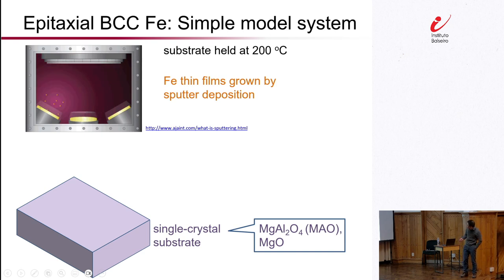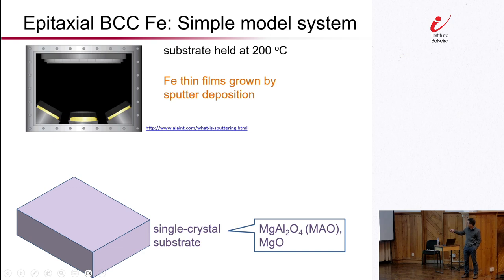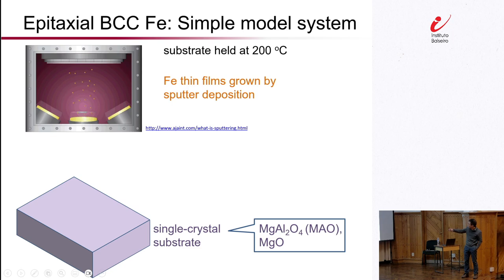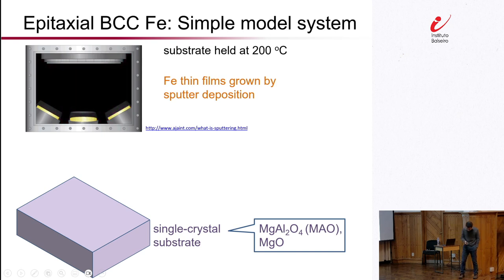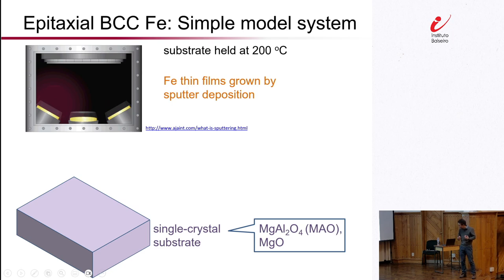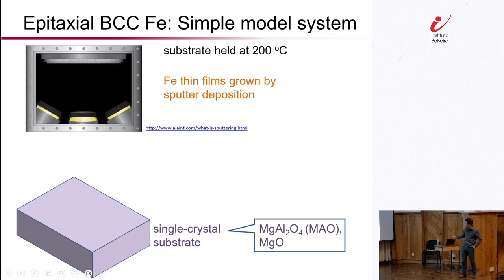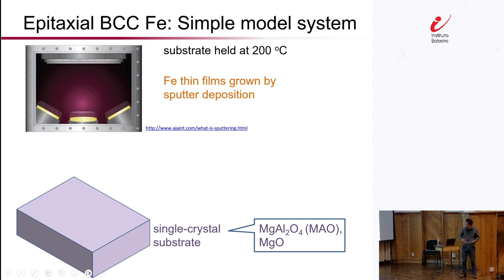Okay, so let me say a little bit about how we make these epitaxial iron films. We use a standard technique of magnetron sputtering, right? So simply coming from bombardment of accelerated argon plasma onto a chunk of iron in our case. We get a plume of iron, we end up with a thin film on the substrate. Now to promote crystallization, promote the growth of epitaxial thin films, we hold the substrate temperature at a somewhat elevated value of 200 degrees Celsius. So this is to allow for all these atoms to find their thermodynamically preferred positions, the BCC crystal structure.